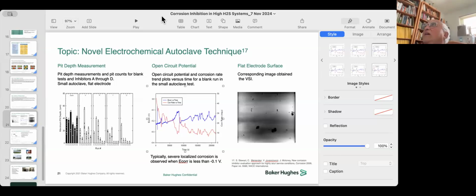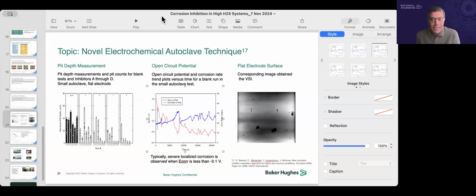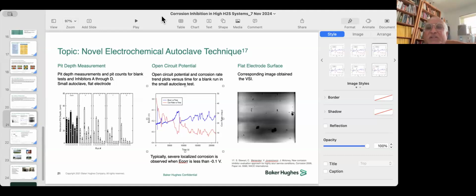In other cases you have film-based inhibition, where you need much more inhibitor and you actually make some sort of film that retards the corrosion, like a passive layer, a precipitant. But since imidazolines work at 10 ppm, at very low concentrations, this is what we proposed: you would have maybe a monolayer or bilayers or multilayers. You'll have a layered system, and there'd be a nice structure.